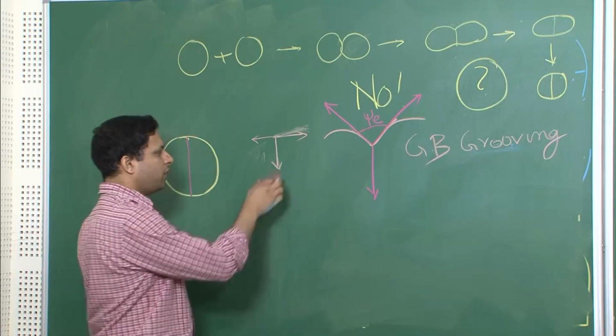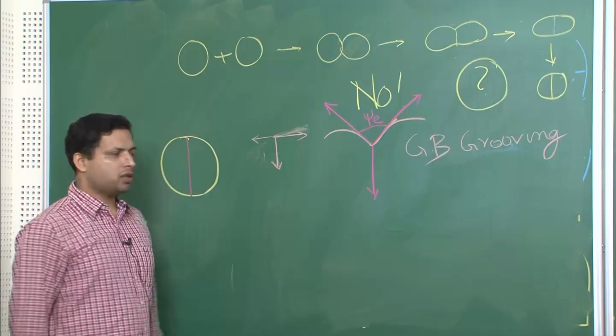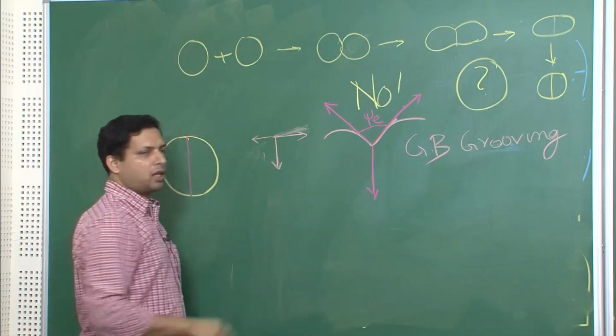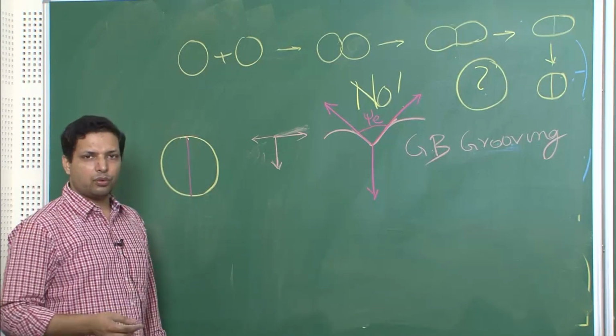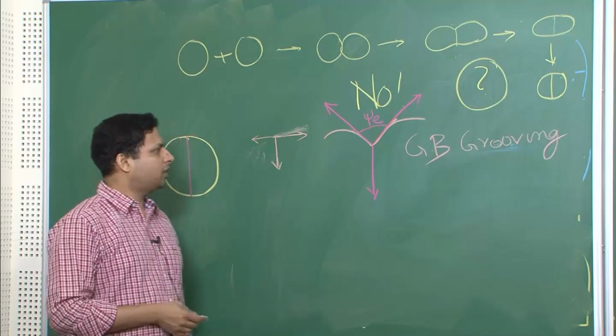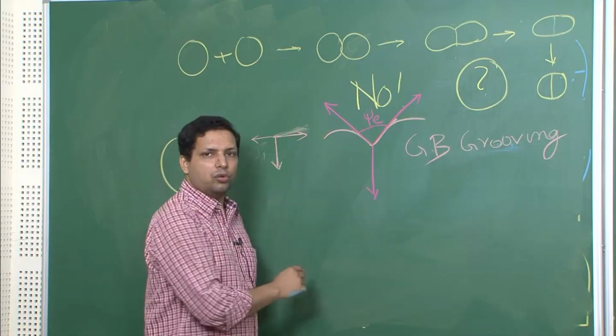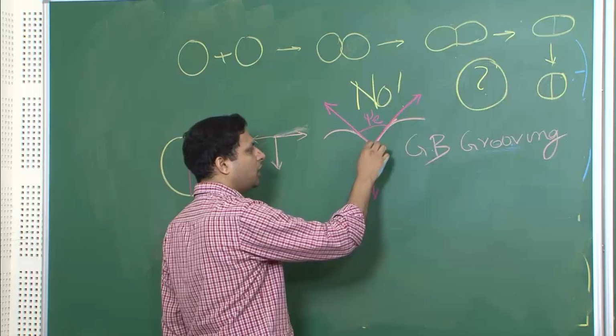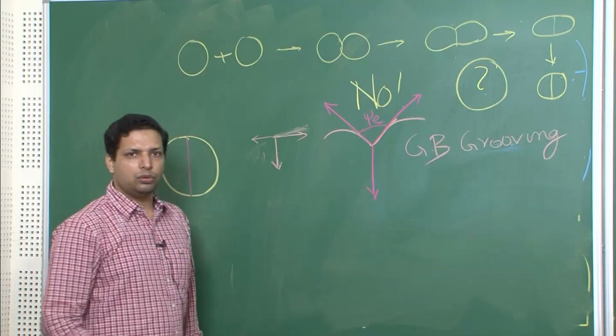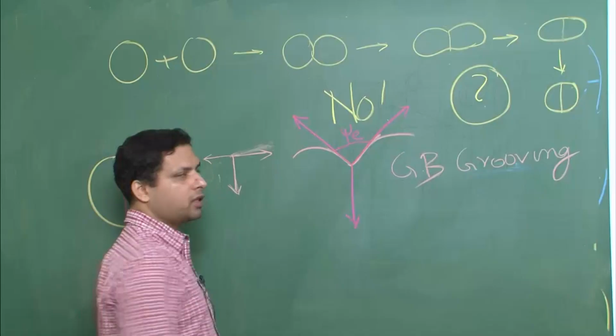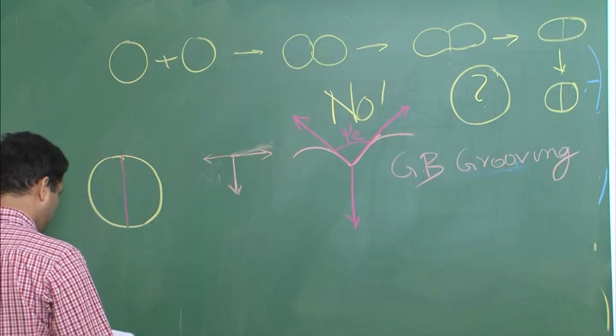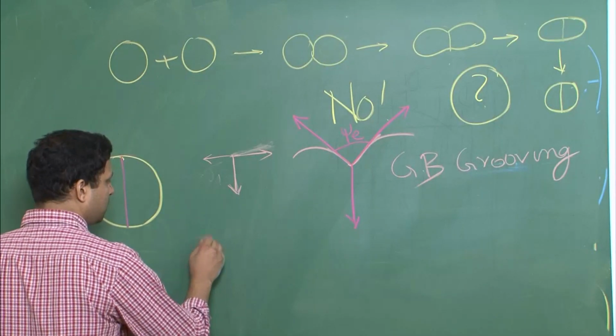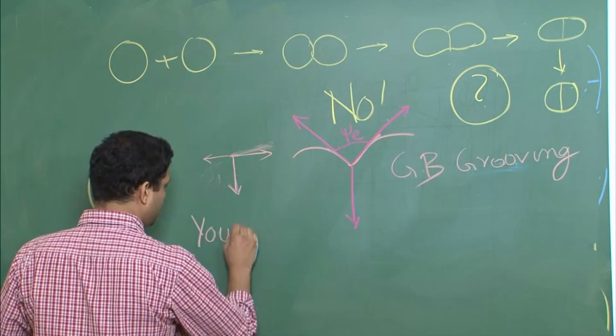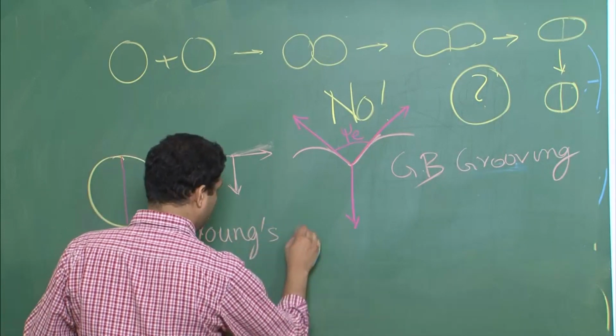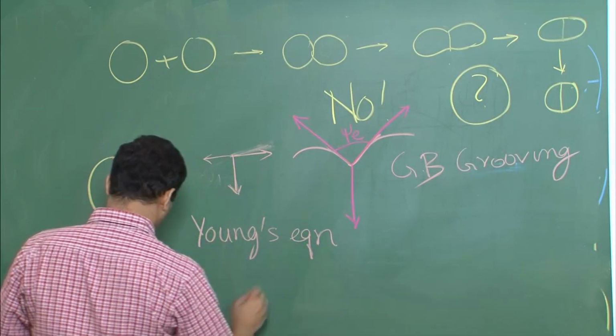So, whenever you have polished a sample, the grain boundaries are exactly perpendicular to the surface, but if you heat the sample just a little bit, the grooving is bound to occur, because the grain boundary energy must be balanced through the other two surface energies. And therefore, from Young's equation, you can write,